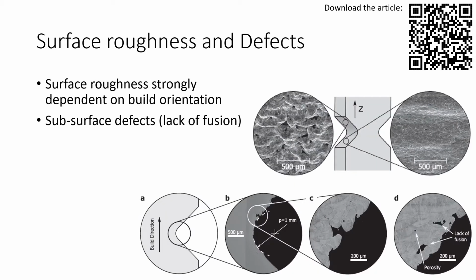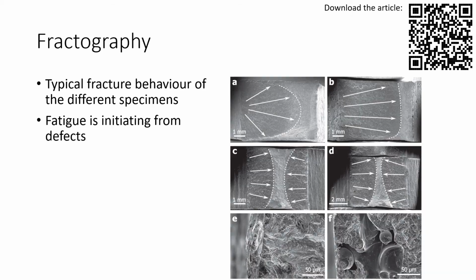If we analyze the different surfaces, what we see is that the downskin surfaces are rough, while the upskin surfaces are kind of smooth. And the lower picture here is a polished cross-section from one of the V-notch specimens subjected to 2 million cycles of loading. And what we see is that the fatigue crack does not initiate from the notch root, but from a defect in the downskin region.